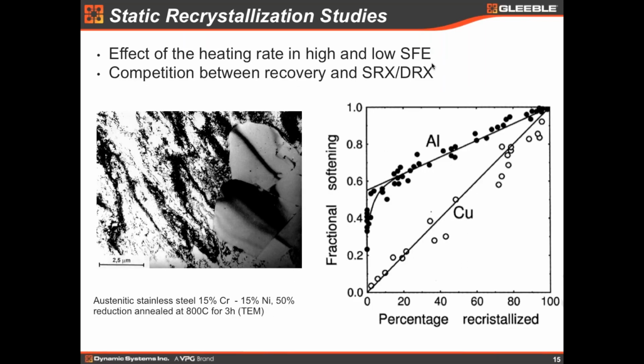Another point that you can study is the effect of the heating rate on high and low stacking fault energy metals, and also estimate the competition between recovery and recrystallization. These two factors are very important in industrial processing. Just as an example, this is a low stacking fault energy metal, stainless steel, and we know that recovery happens very slowly in the deformed zone, so it will not lose the driving force. So you keep the driving force and you keep the recrystallization progressing.